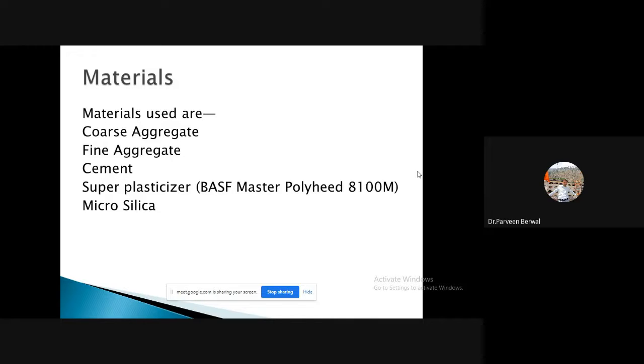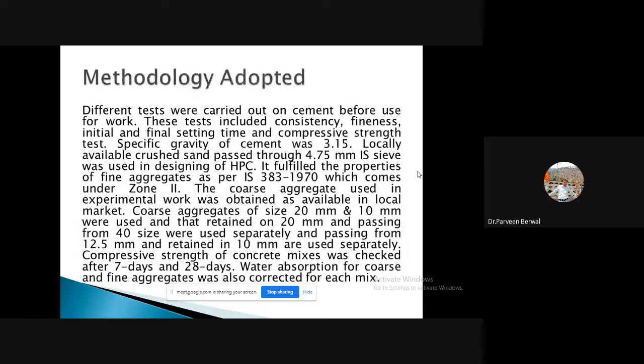Also, the materials we use are the fine and coarse aggregate, the cement, the superplasticizer Polyheed 8100M and the microsilica. If we talk about the methodology, there are different tests that we use: for consistency, the initial and final setting time, and the compressive strength. These are the tests that we use in the present study. And talking about the coarse aggregate, we use 10 mm and 20 mm, and the compressive strength is generally checked for two ages, that is 7 and 28 days.